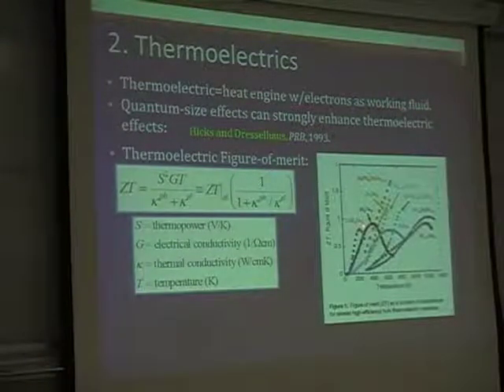So here are some of the best thermoelectric materials, and you see that ZT is not approaching infinity. It's actually more like approaching 1 in the best materials that there are. And unfortunately, a ZT of order 1 is not really competitive as a heat engine with more traditional heat engines based on compressing gases. So that has meant that thermoelectrics are basically a niche field. They have not replaced more traditional heat engines. But they have their applications, such as in space probes, where you don't want to carry around a compressor and so on.